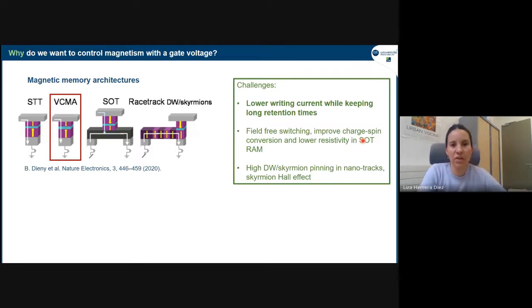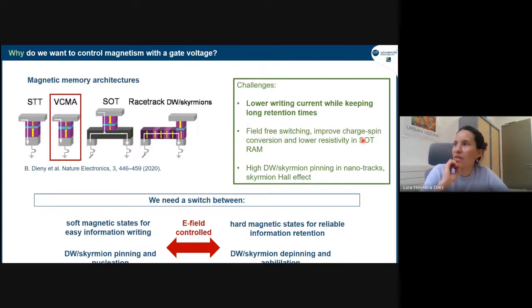So where is electric field control of magnetism here? One of the main selling points for applications is that it can provide us with a switch that can give us different states of magnetic anisotropy that could be used, for example, for toggling between a relatively soft magnetic state where we could write information at a relatively low energy cost, but without having to compromise reliable information retention. Because once we write the information we want with low writing current, we could switch back to a relatively hard magnetic state where anisotropy is much higher. And that state will keep the information for a very long time in a very reliable way. So we wouldn't have to compromise anymore between these two things. The E-field control will allow us to go from one to the other.